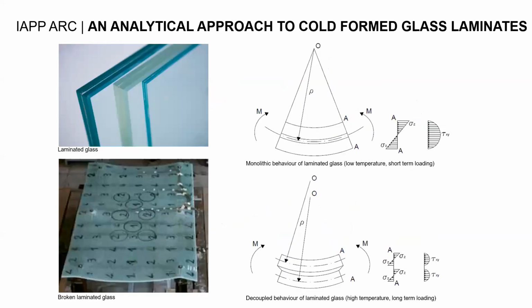My work was looking into the specifics of cold bend glass and warm bend glass. So I developed an internal tool to look at the loss of shear bonds in the long-term loading of laminates. So basically, in short term, a laminate behaves like a full, close to full, if not a quite good composite. And in long term, there's a loss of shear at interlayers, and this is what I studied. So how does all that we know there affect glass design and paneling in the long term?